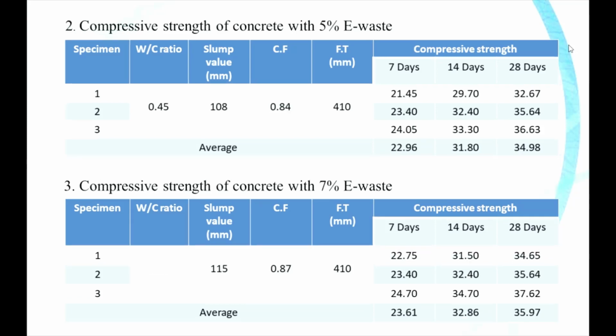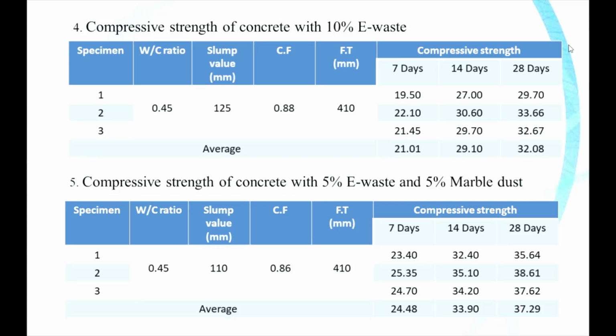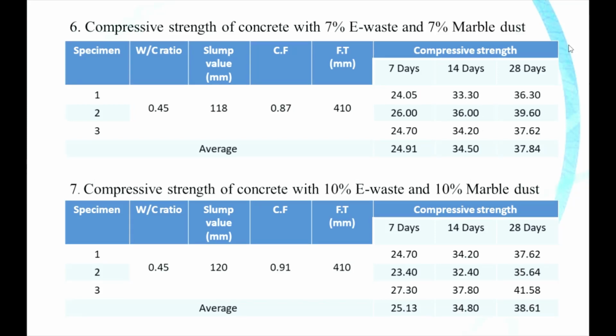So as compared with the previous table, there is an increase in strength. As we compared it with the second table, there is an increase in the strength as we add the 5% of the marble dust. So moving towards the next slide, that is table number 6. In this there is a compressive strength of concrete with the addition of 7% of e-waste with 7% of marble dust. In this there is the same water cement ratio 0.45, slump value of 118 mm, compaction factor value 0.87, flow table value 410 mm.